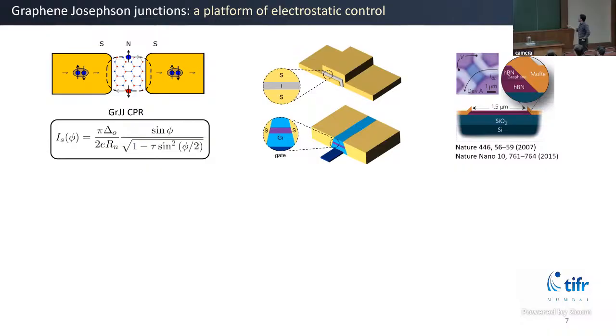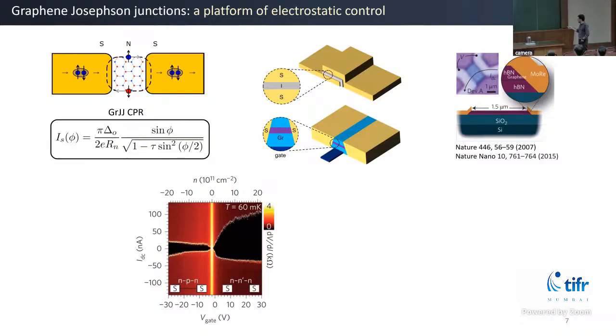People started making graphene Josephson junctions in 2007, and they found that in these JJs you can get a gate-tunable critical current, because graphene is a 2D material where you can add carriers and dope it locally, and that tunes the critical current. What you are seeing here is a critical current map of the Josephson junction as a function of gate voltage. In this black region, the junction has zero resistance, and this boundary that you are seeing is the critical current of the junction.